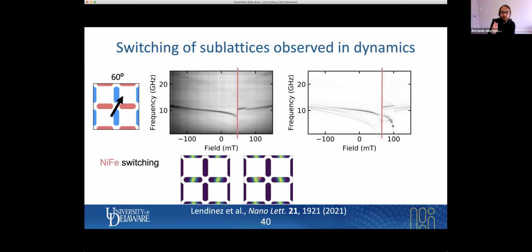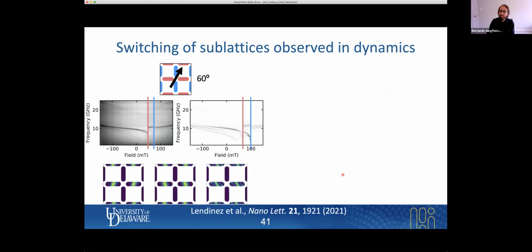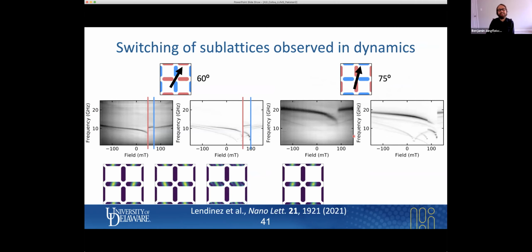And as we increase the field further, there is the step-down line feature, and that's when the cobalt iron switches here. And remember, the cobalt iron is in the vertical elements, and it affects the dynamics in the horizontal elements. And we see now the formation of a higher order mode in the horizontal elements. We can also do this for the complementary lattice. So let's take a look. So we have here 75 degrees.